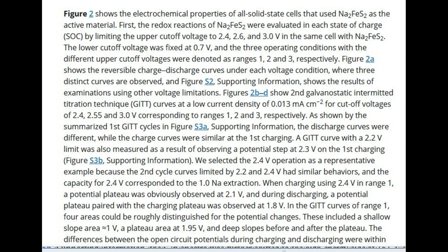Figures 2b-d show second galvanostatic intermittent titration technique, GITT, curves at a low current density of 0.013 mA cm^-2 for cut-off voltages of 2.4, 2.55 and 3.0 V corresponding to ranges 1, 2 and 3, respectively. As shown by the summarized first GITT cycles in Figure S3a, Supporting Information, the discharge curves were different, while the charge curves were similar at the first charging. A GITT curve with a 2.2 V limit was also measured as a result of observing a potential step at 2.3 V on the first charging, Figure S3b, Supporting Information.